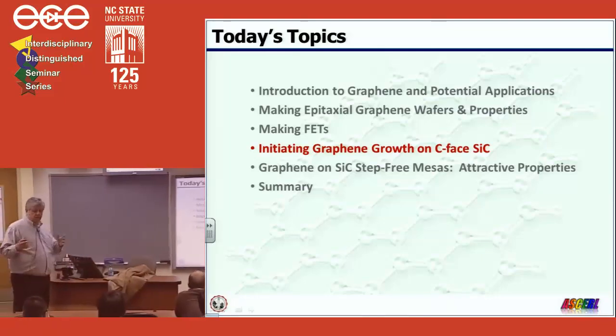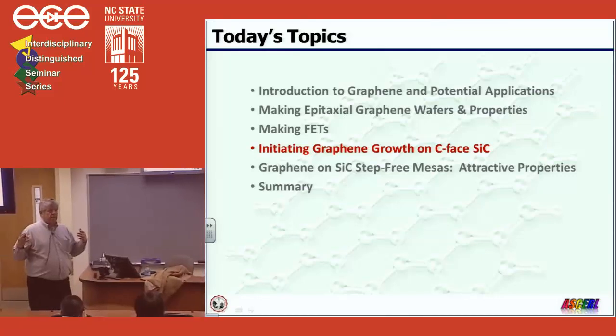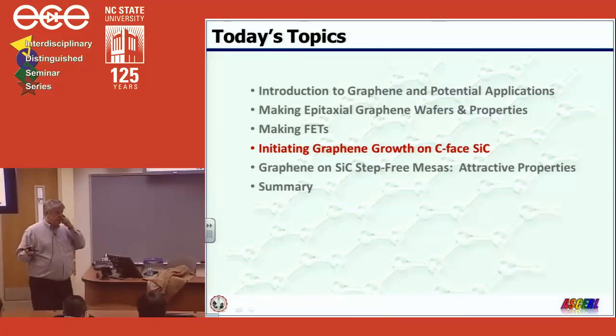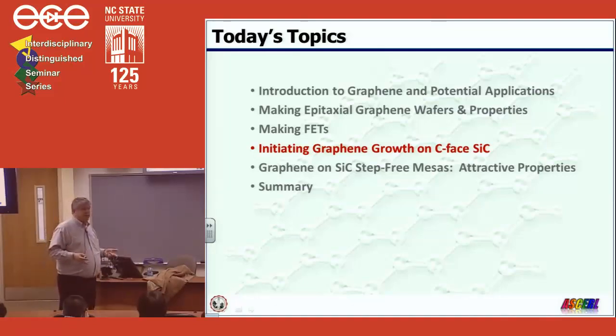Okay, so graphene has a lot of very interesting properties, and we can grow it on silicon carbide, and it means we have a wafer that we can process using standard techniques. We've been doing a lot of work on the silicon face because it has a more uniform morphology, it's not very rough, it's only 1 or at most 2 layers, and so we can do a lot with it, although it's limited in terms of its transport properties compared to the carbon face.